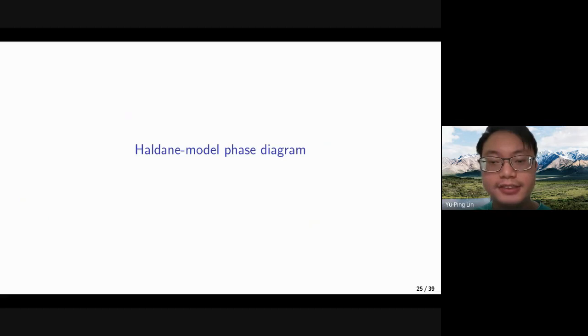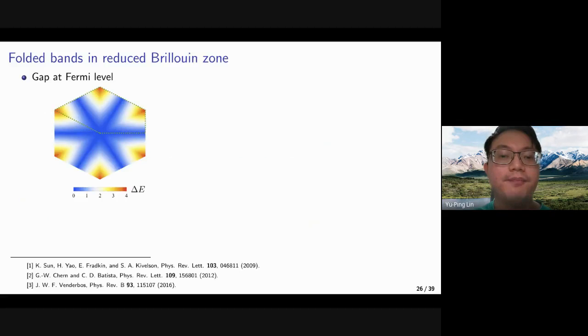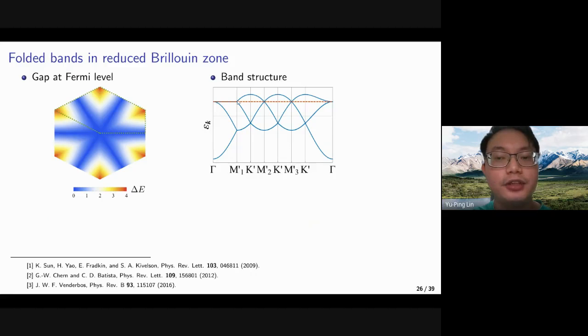I'll show next that we have a Haldane-model phase diagram here. To look at the density wave, we need to first look at the reduced Brillouin zone. So we have to fold the bands in the original Brillouin zone into the half times half reduced Brillouin zone. And we see that we have 3 Fermi lines at the Fermi level, which cross at the gamma point. And indeed, if we look at the band structure along the gamma-M lines, there will be a flat line, and we have some nodal points at the endpoints.